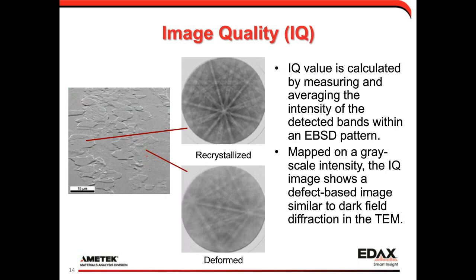The first measurement I want to talk about is what we call EBSD image quality, or IQ. This is a value that measures the sharpness and intensity of the diffraction bands in the EBSD pattern. You can see in the example here, in a recrystallized part of the material where the crystallographic lattice is very pristine, we get nice sharp diffraction points. If the material is deformed, the lattice is a little curved, the diffraction becomes a little more diffuse, not as sharp, not as bright. And so that would cause a lower image quality value.